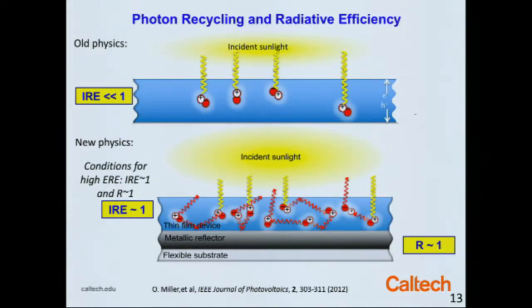The new physics is that if we work with a material that is sufficiently luminescent, and we trap it inside a material between a mirror, a highly reflecting mirror with reflectivity close to 1, and we have a radiative efficiency—in other words, conversion between photons and electrons and holes back to photons inside the material—approaching 100%. In gallium arsenide, that number can be 99.9%, actually.